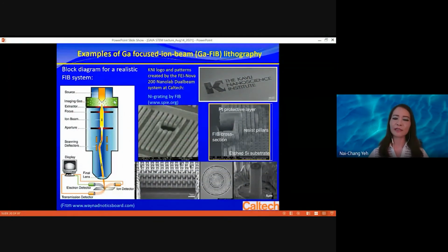So this is also the schematic of how it works. You have the source of gallium coming out, and then you use electrostatic fields to focus the beam and to control the beam, and you can scan the beam across, and then you hit the sample. Then there are different collectors, detectors for the ions and electrons, secondary ions and secondary electrons. And so these pictures show these features. You can imagine if I originally have a flat wafer and now I want to remove a lot of material, then a gallium ion beam is very useful, and then you can make all kinds of complicated structures. And these complicated structures are not easily done by photolithography. So these three-dimensional structures are much easier done by focus ion beam